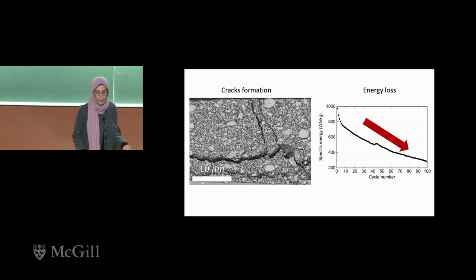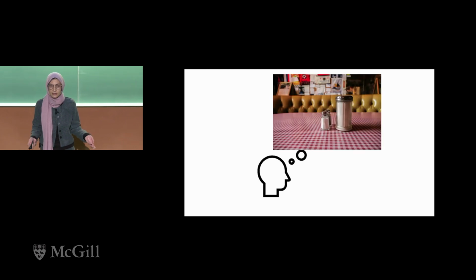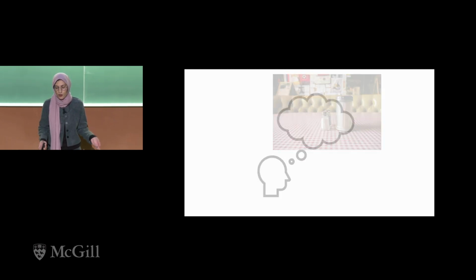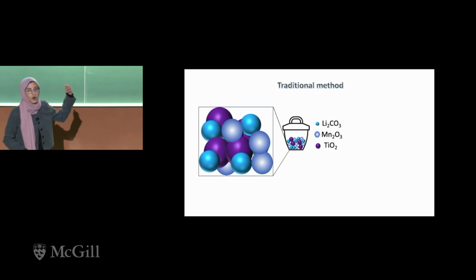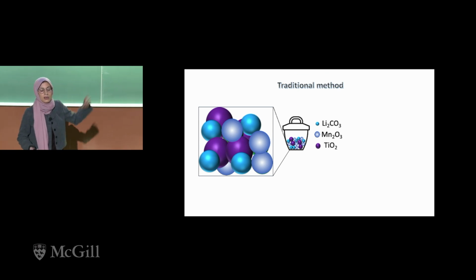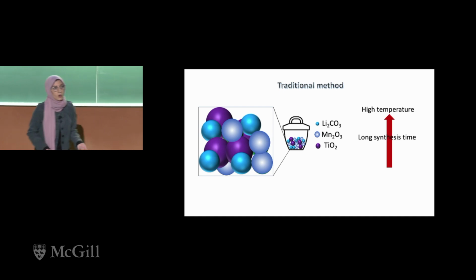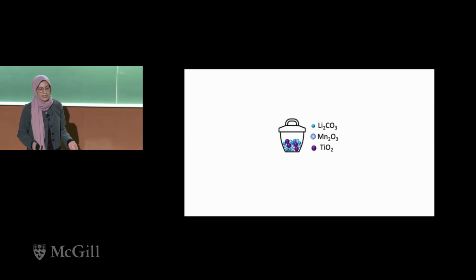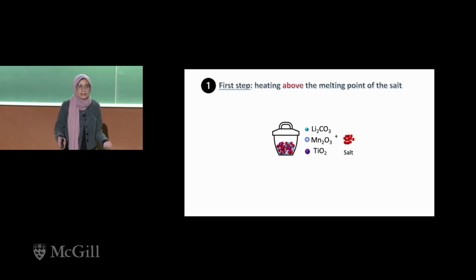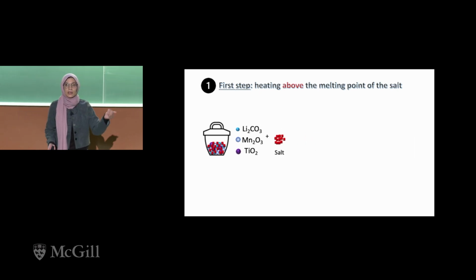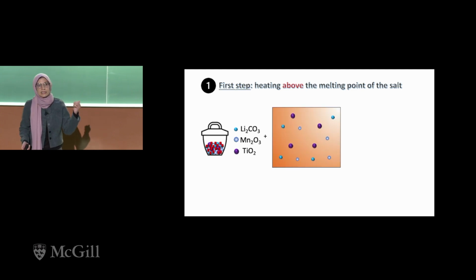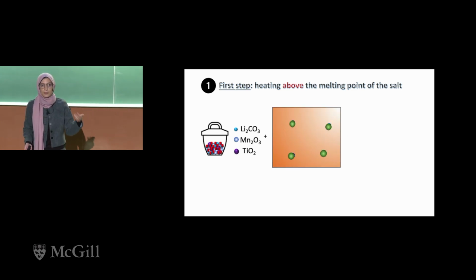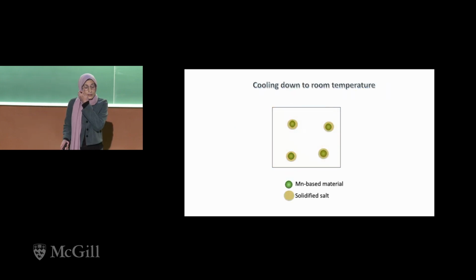So what is the solution? Here is where my PhD project comes in. The solution is simple. It is the salt. Yes, like kitchen salt. Instead of mixing the solid precursor for a long time and at high temperature to synthesize the material, which led to large particle formation, we add the salt to the precursor. Then we heat the precursor and the salt above the melting point of the salt. The molten salt will facilitate the ion diffusion and speed up the reaction, reducing the reaction time and temperature from 1000 C for 12 hours to 800 C for 1 minute.